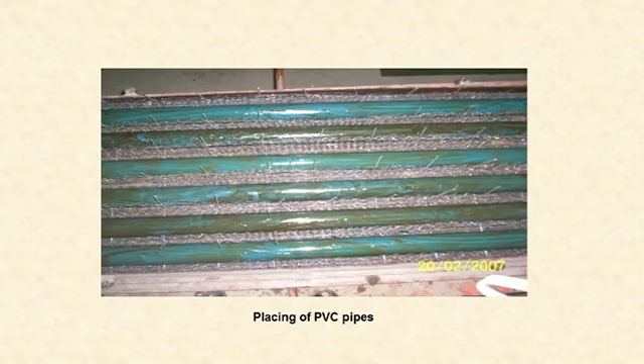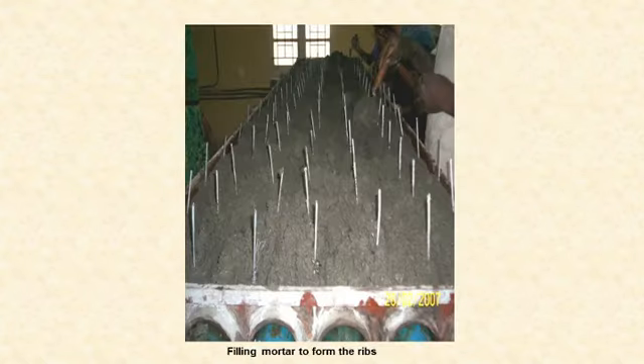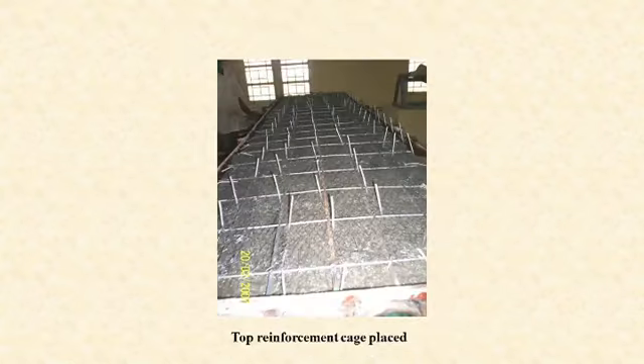The PVC pipes were inserted through the openings made in the mold to make the hollows, and cement mortar was spread to form the ribs. Since the mold was kept over the vibrating table, a few seconds of vibration were given for compaction.